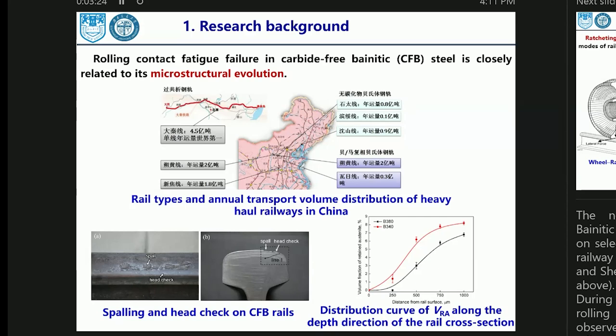In addition, we also find the volume content of the martensite on the surface is lower than in the other areas, and as the depth of the position increases, the volume of the martensite increases. So the rolling contact fatigue is related to the microstructure, like the martensite or the retained austenite.